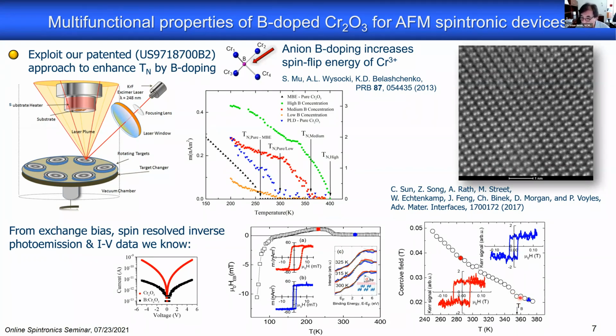What that means is, yes, the system was magnetically ordering significantly above 307, and yes, there was interaction between the ferromagnet and the antiferromagnet, but it was just not a system that was able to pin the ferromagnet on its reversal. Then we said, well, that may have something to do with the orientation of the boundary magnetization. Maybe it's no longer fully perpendicular, maybe it's somewhat tilted. And indeed, we grew in-plane anisotropic, the regular exchange bias systems, and we saw exchange bias coming back, even sizable exchange bias coming back, but not at the temperatures that were beneficial in the sense that the doping made sense. So the exchange bias pathway was basically done for the boron doped material.